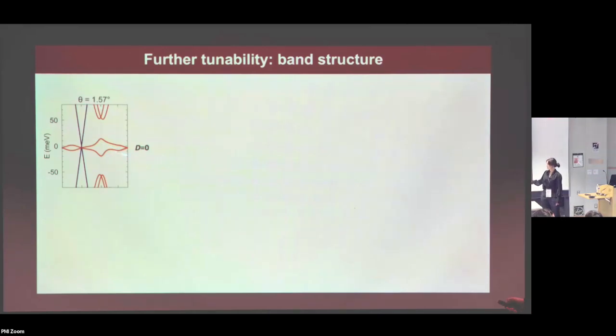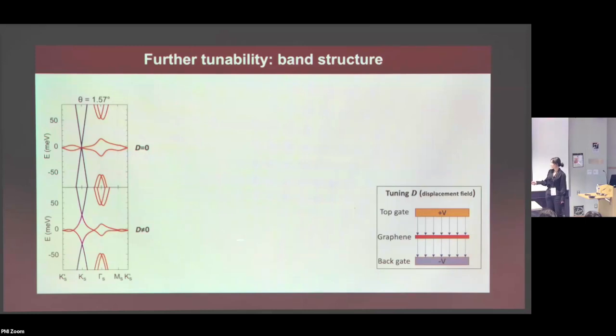And the separation between this flat band and Dirac band is actually protected by the mirror symmetry of the system. But once you break that mirror symmetry by applying the so-called displacement field, a perpendicular electric field to the device, there's no longer that protection. So then these two bands start hybridizing. So by controlling this displacement field, you can tune the bandwidth and the band structure continuously in situ.